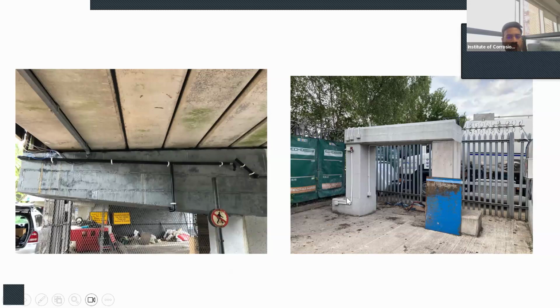Another system is this, where we again use this conductive coating system, and we have these conduit cables. Again, you will see that anode wire was installed using pins to hold them, and then glass fiber tape was used to protect it from mechanical damages, and then the second coat of paint was applied.